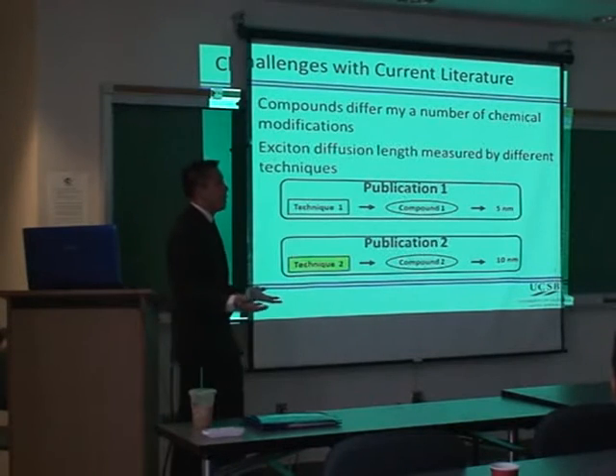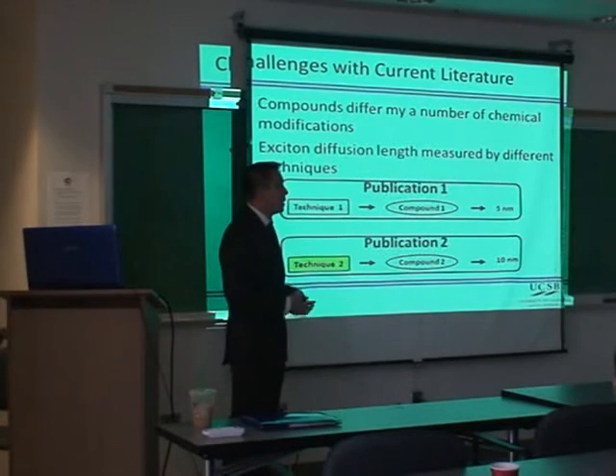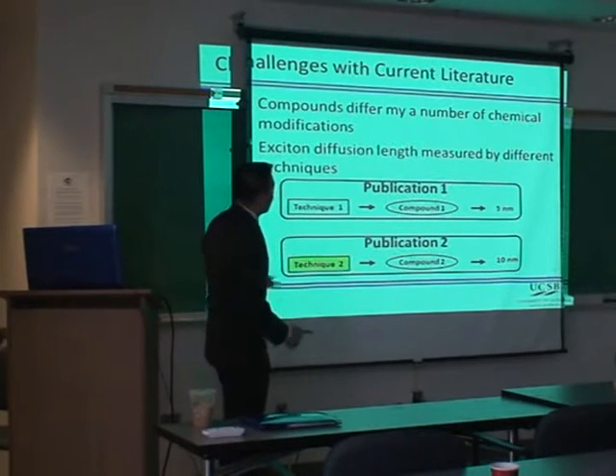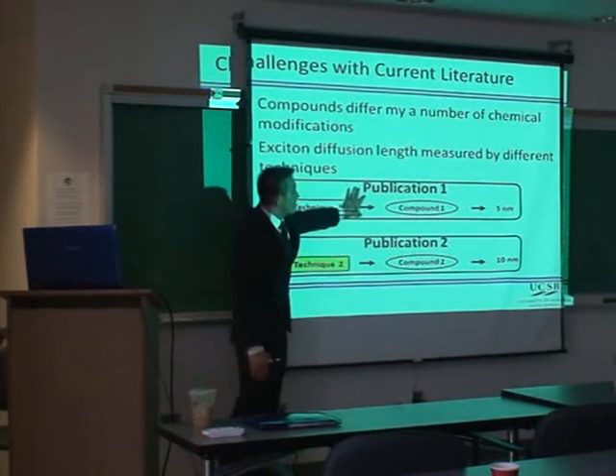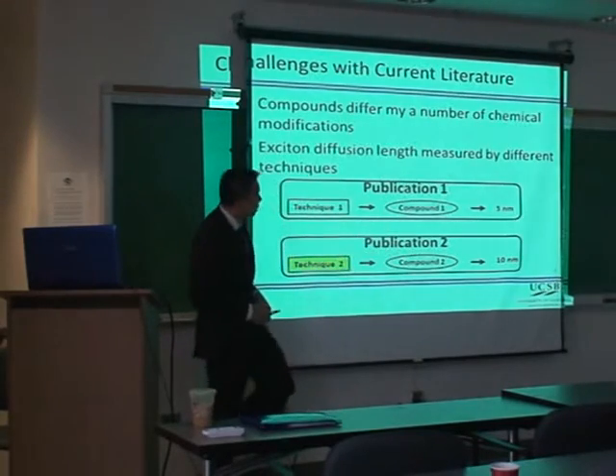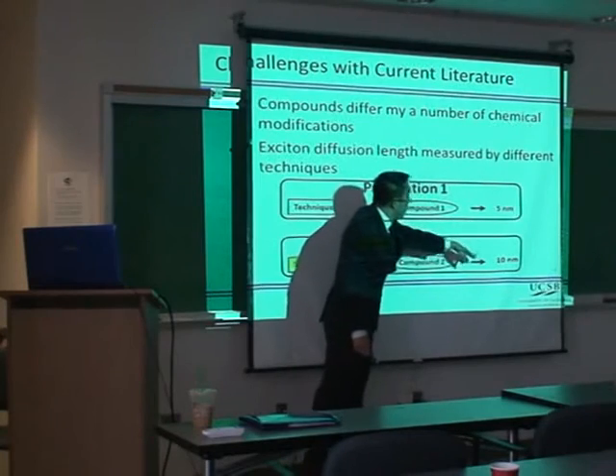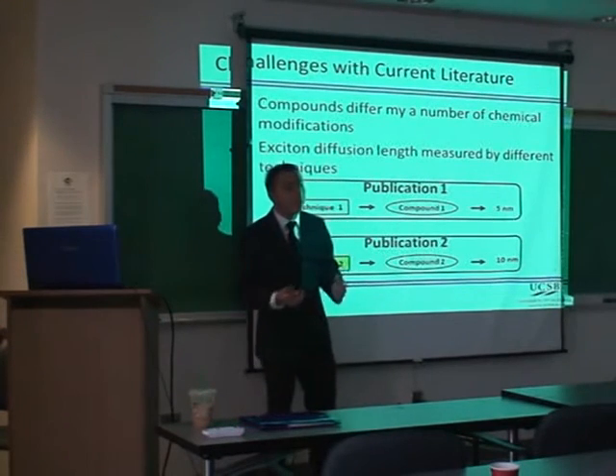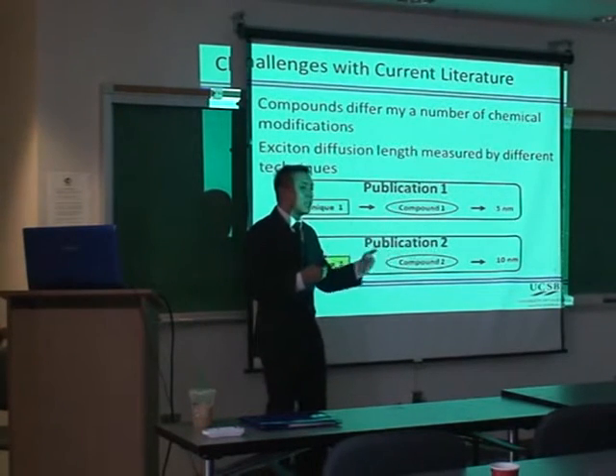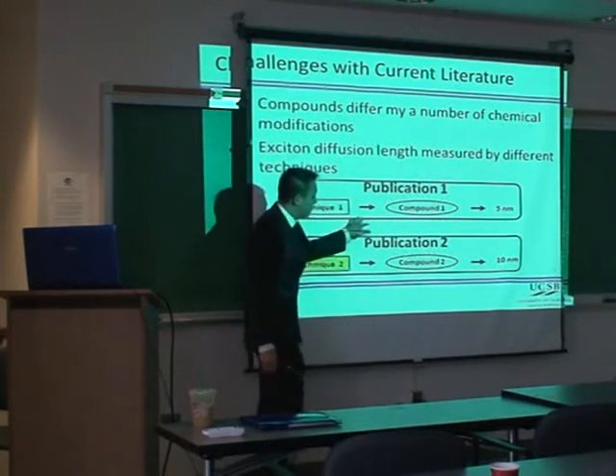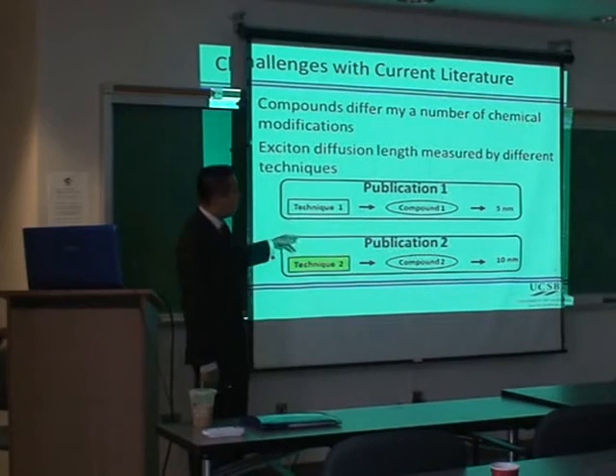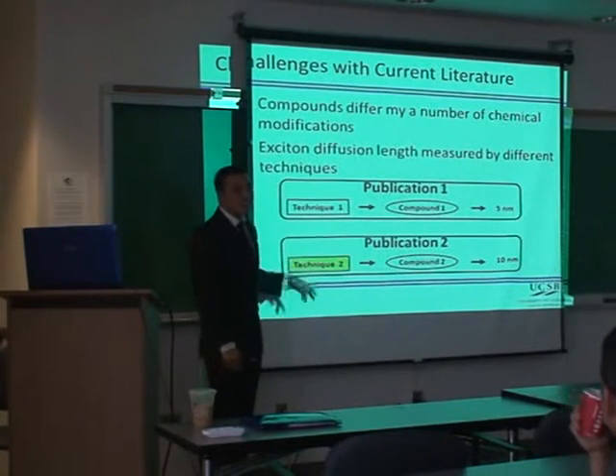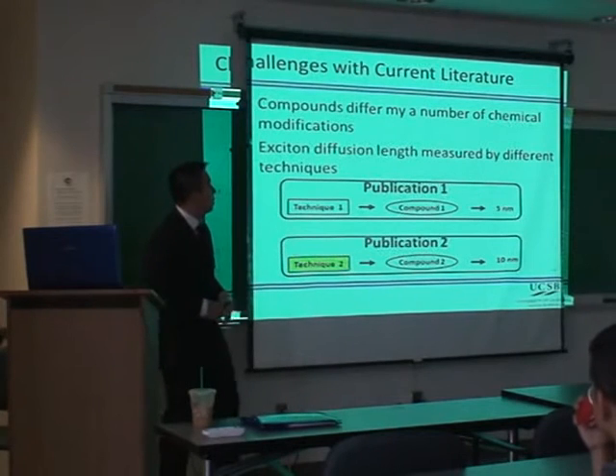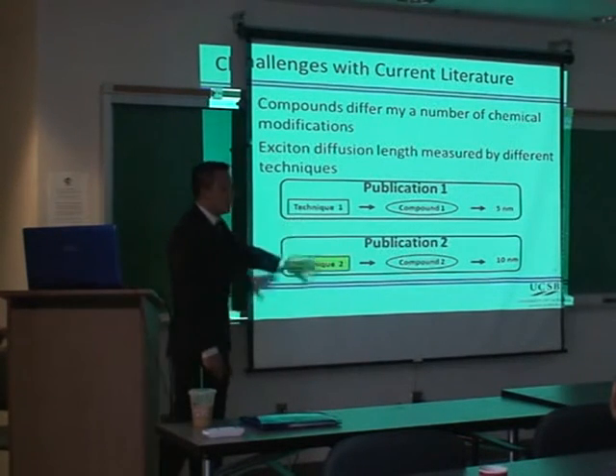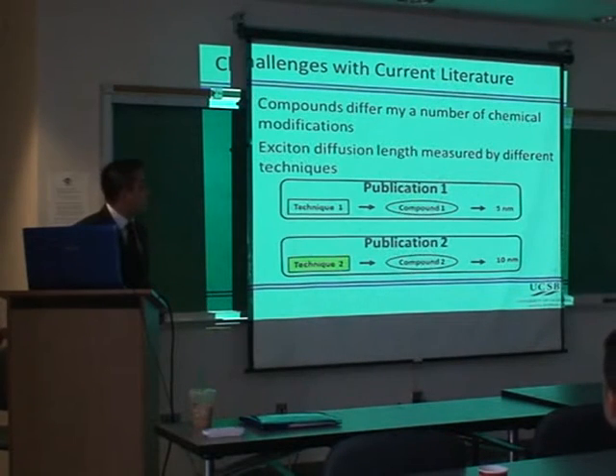So, of course, we can actually study this already with literature, because there's been a lot of publications of exciton diffusion lengths in different materials, but there's challenges with that, because, for example, you have 2 different publications, 2 different compounds. Let's say we want to compare the exciton diffusion lengths of these 2 compounds. One was 5, one was 10. Well, this sometimes is challenging because these chemical structures could be very different from each other. They could differ by a number of chemical modifications. So it's hard to tell how one chemical modification impacts the exciton diffusion length. In addition, it's further complicated because there's so many techniques to measure exciton diffusion length that it's a very good chance that they use a different technique. So that makes it even harder to compare the 2 molecules to one another. So those are the 2 difficulties of using current literature to study exciton diffusion length.